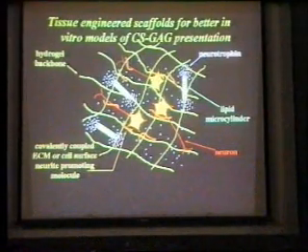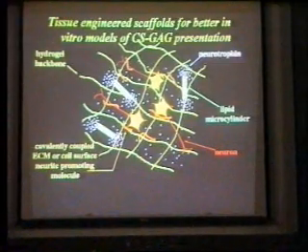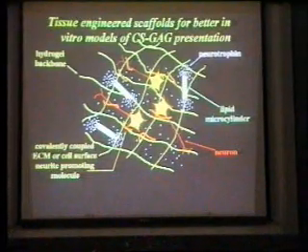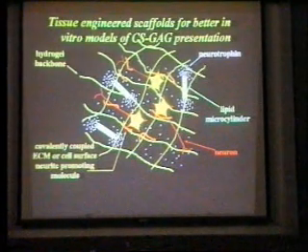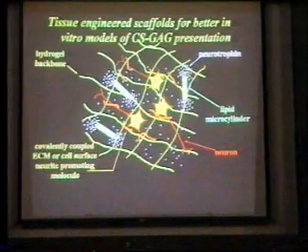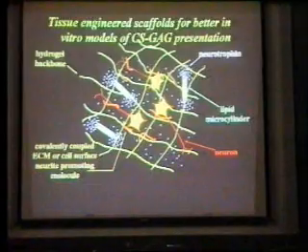And we compared what happens when you have equimolar amounts of different GAGs in such a gel, and you put neurons inside, so that you get a sense for the potency of the gel. We did not put in the gel, which we could have done, the ratio of the GAGs we saw. We put equimolar amounts. There's no question of attachment now because the neurons are trapped inside the gel. So you're able to separate the issue of growth cone inhibition from initiation of growth or attachment.